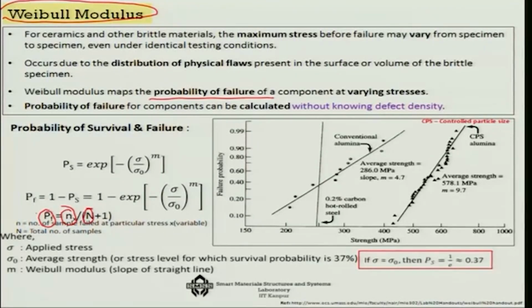Now, if I know PF, and I know that the probability of success is the reverse of PF, that is, it is 1 minus PF, then I know the PS. If I know PS, and I know the average strength sigma 0, which is known to me, and I also know the applied stress value at which I am calculating this, then by a simple log plot, I should be able to find out the slope of this line. That means I should be able to find out the value of m.